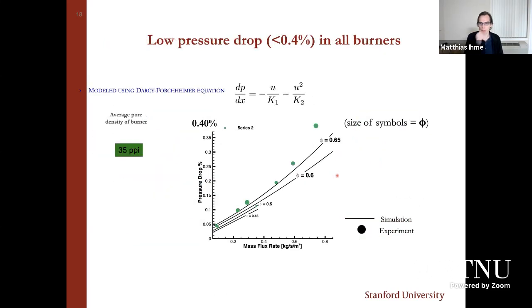For combustion applications, pressure drop is an important factor. We measured the pressure drop for these experiments, and what you can see here is that the pressure drop doesn't exceed 0.4% with respect to the inlet pressure. So this is a rather small pressure drop, and as a matter of fact, it matches the Darcy-Forchheimer relation quite well, giving us confidence that this is a very reasonable estimate to assess the pressure drop.